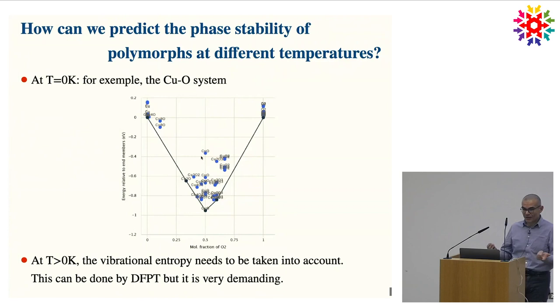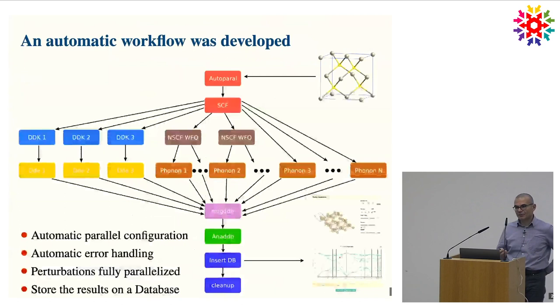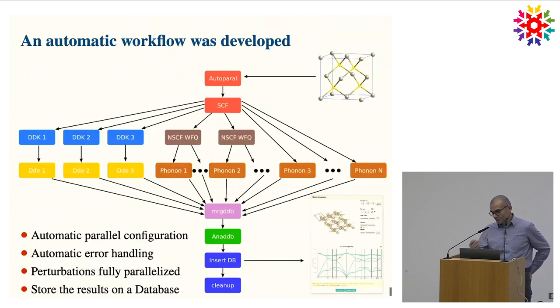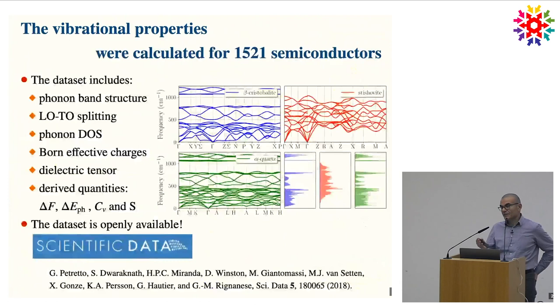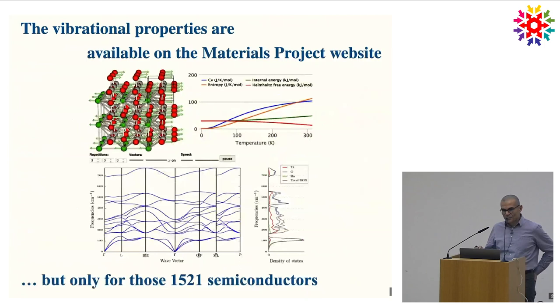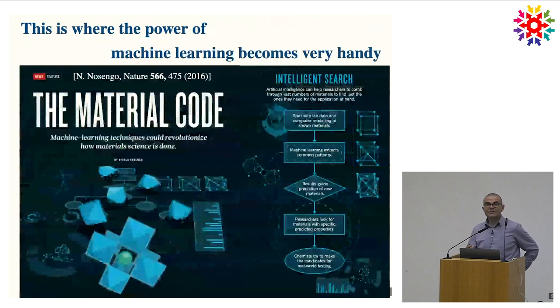It would be more desirable to have stability as a function of temperature, because we don't live at zero K — we live way higher. We need to take the vibrational entropy into account, which is possible from DFPT calculations, but very demanding. We developed a high-throughput workflow to compute phonons. That takes quite a lot of CPU time, and we released that for only 1,500 compounds — that was millions of CPU hours. It's available on the Materials Project, with input/output also available on NOMAD.